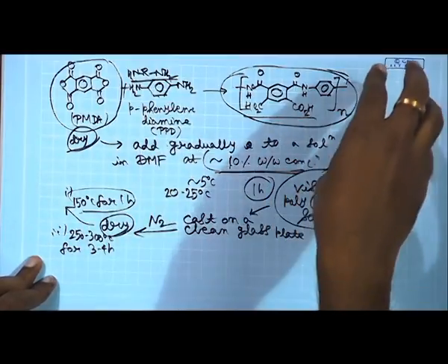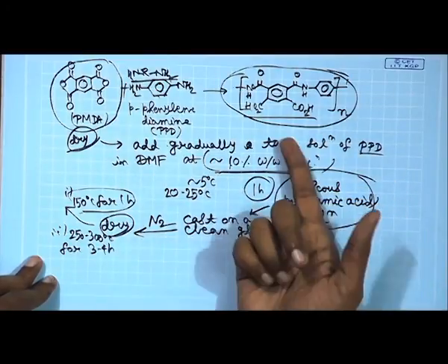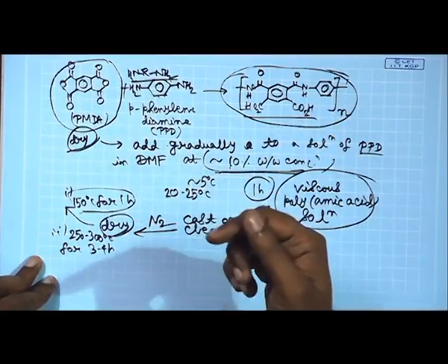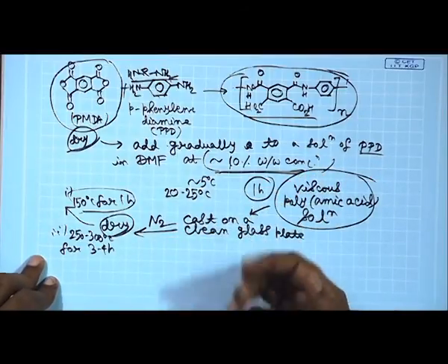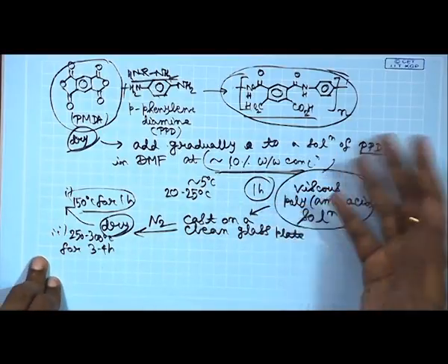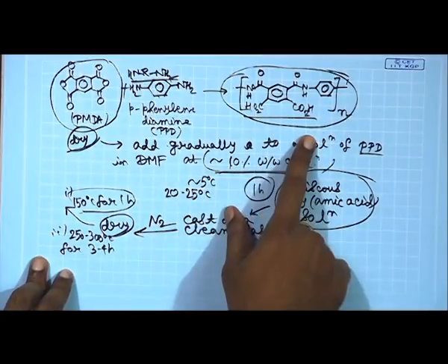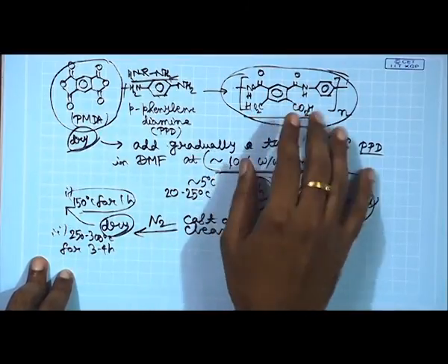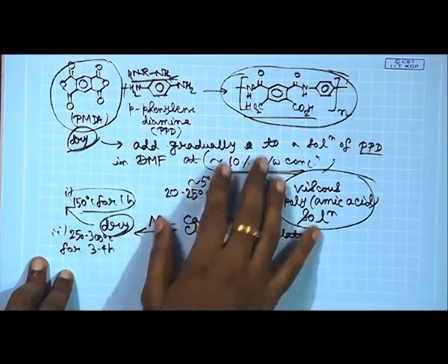Instead, if you had produced polyimide directly and tried to start processing, it is difficult, because first of all you will not reach high molecular weight, because before high molecular weight it starts to precipitate out because of solubility problem in the solvent. Secondly, even if you could get high molecular weight, it is now insoluble and you cannot melt this material either. So, what will happen? You cannot process it. That is why you start with polyamic acid, which is still soluble and can still be melted, and then you take it into the desired shape, you remove your solvent, you heat it up, cyclize, and you get your final product in the processed condition.